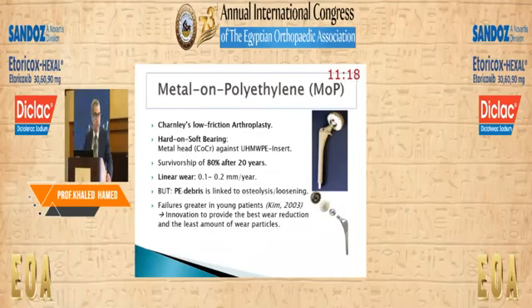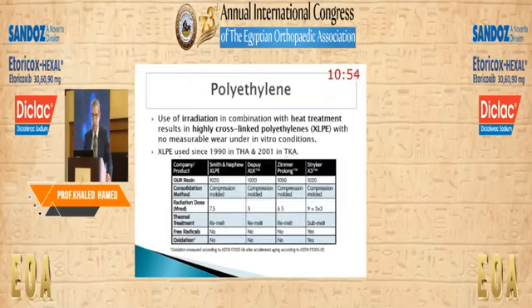It offered a survivorship of 80% after 20 years, and the linear wear was 0.1 or 0.2 millimeter per year. But even this 0.1 millimeter is enough to cause millions of particles that may end in osteolysis and loosening. So it was a problem in young patients, and the innovation was to provide the best wear reduction and the least amount of wear particles. Using irradiation in order to sterilize polyethylene, it resulted in heat treatment and the formation of highly cross-linked polyethylene with no measurable wear under in vitro conditions.